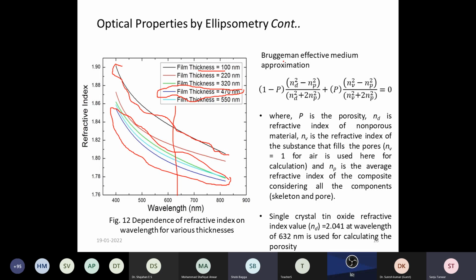And using the Bruggeman effective media approximation, we can convert this refractive index into porosity, P. P is the porosity, Nd is the refractive index of the non-porous material, Nv is the refractive index of the substance that fills the pore, or air is used here for calculation, while Np is the average refractive index of the composite considering all the components. Here we have used Nd 2.041 at 632 nanometer.